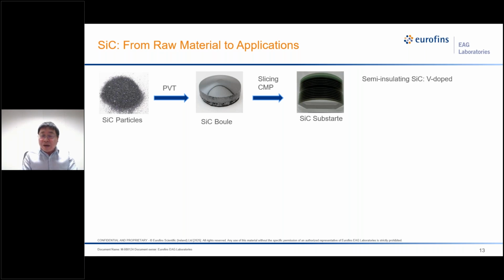There are two types of silicon carbide substrate available. One is the semi-insulating silicon carbide. Vanadium, titanium were doped to control the resistivity of the substrate because it's hard to get a pure silicon carbide substrate. This substrate is used to grow gallium nitride epi layers for high electron mobility transistors. Another type is conductive silicon carbide. For this type of silicon carbide, nitrogen is doped.